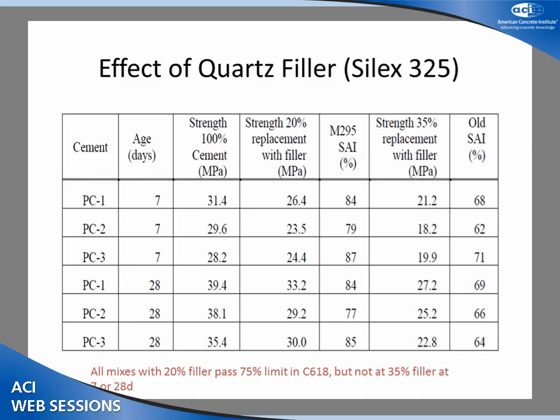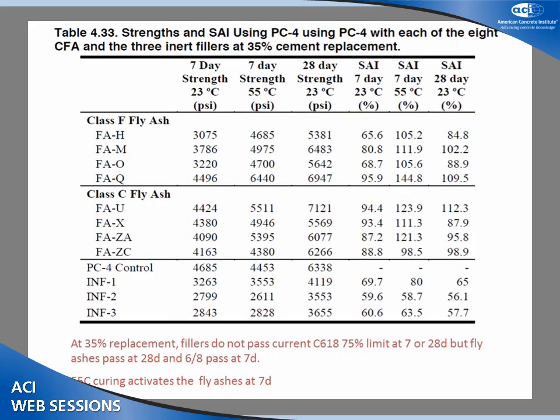And so they wouldn't have passed the old strength activity index under the old system. Okay. We tried just for fun. We did it with three different fillers, and we got different results. Some fillers work better than others, but you couldn't distinguish the fillers from some of the fly ashes in that case, especially the 7-day test.